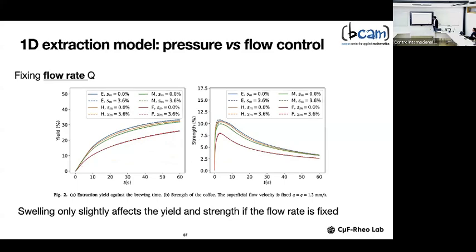If you impose a constant flow rate, however, you can see that swelling has almost no effect. And this, of course, from an engineering point of view, makes sense, because enforcing the pressure is a way to drive the liquid, but you don't know anything about the microstructure, about the effective time-dependent resistance that will be developed within the coffee bed because of fine migration, because of swelling, because of erosion, etc. So controlling the flow rate instead of the pressure drop produces results which are much less dependent on variations that cannot be controlled.